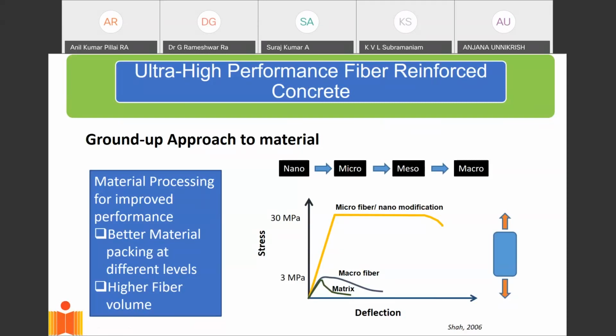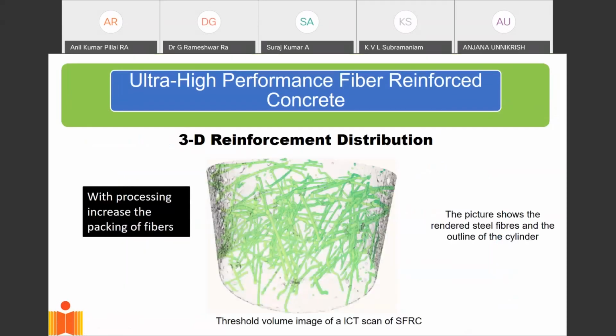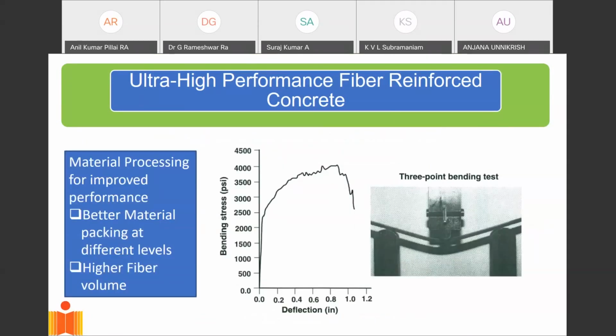And this UHPC can only be achieved by processing, which requires packing a lot of fibers into a volume of concrete. I'm just showing you a CT scan of what one of these UHPC materials looks like, with a very high fiber volume packed into a very small volume of the material. And one is able to achieve this level of ductility. This is a small, very thin beam made of UHPC, which starts deforming like a steel beam.